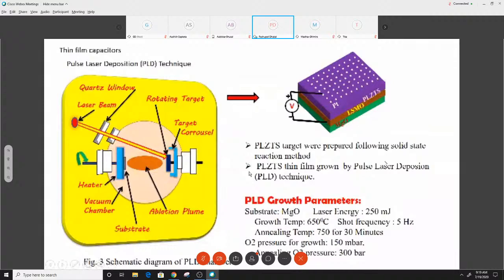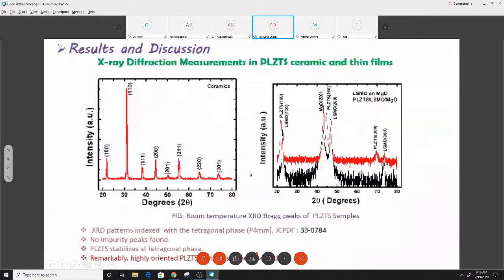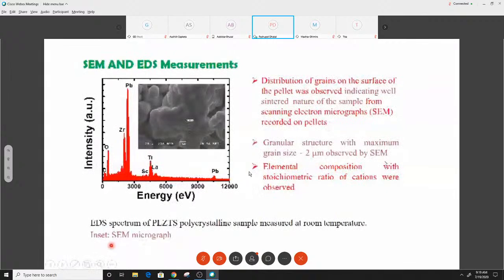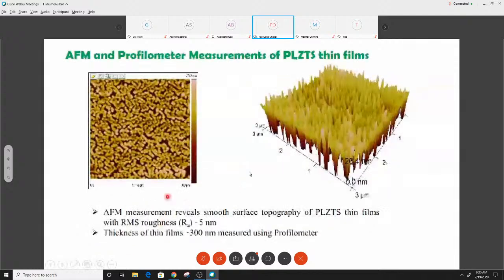This is the X-ray diffraction measurement of the ceramic capacitor and thin film capacitor. We check the phase purity of the materials with this technique. This is the SEM and EDX measurement of the ceramic. We got a grain size of the ceramic of around 2 micrometers, and elemental analysis was carried out with the EDS measurement. Surface topography of the thin film was analyzed with AFM measurement, and we got around 5 nanometers roughness of the thin film, and the thickness of the thin film was measured with a profilometer.